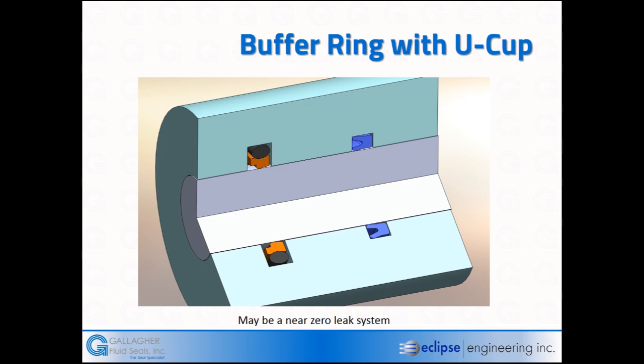And finally, this is just a cross-section of the two seals in place, which creates a near-zero leak system. That second element, oftentimes customers will just have a urethane U-cup, but under high load, with a high cycle rate and high pressure, 2,500, 3,000 psi, that urethane U-cup will typically wear out rather quickly. When we put the buffer element in front of it, we extend the life of that U-cup to at least as long as that PTFE, or that buffering Teflon element. We've extended the life of the urethane elements by 3 to 4 times its standard life by putting that PTFE element in front of it.